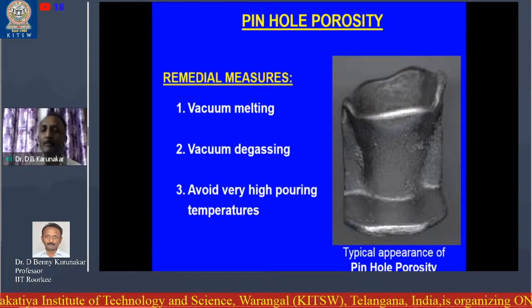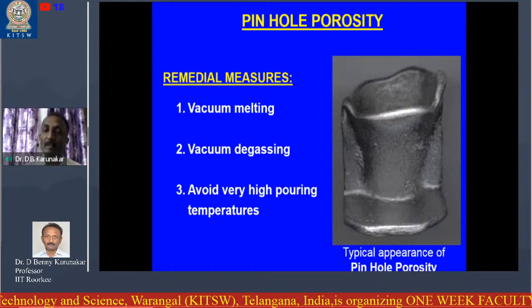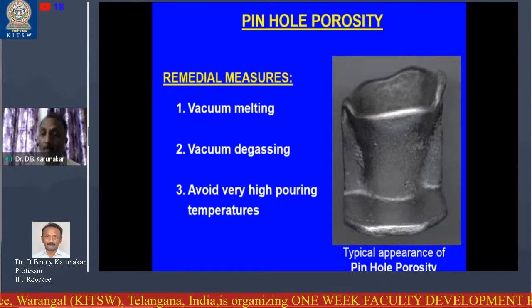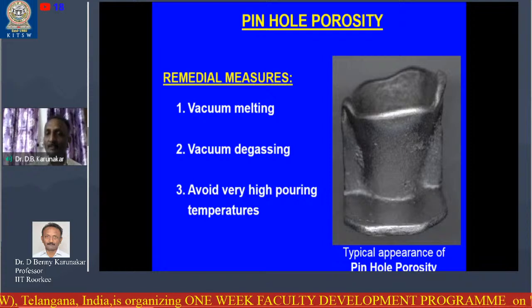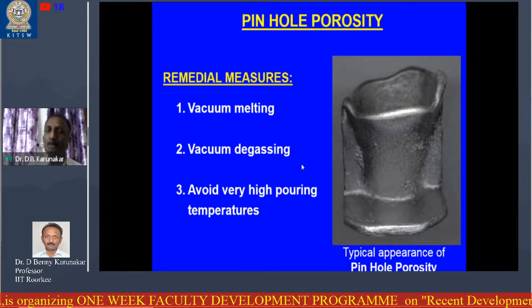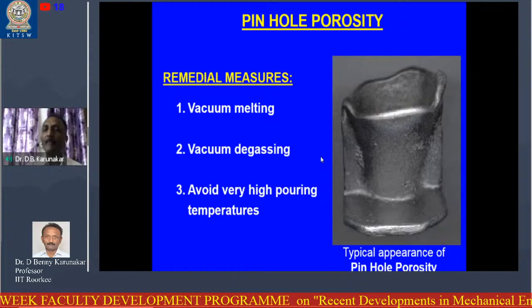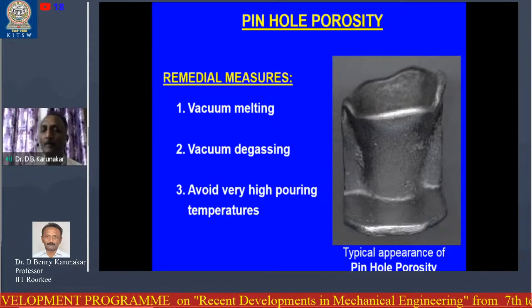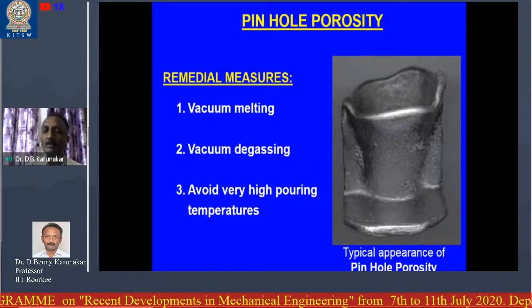What happens if someone heats it up to 850? It overboils. Then it accumulates air bubbles inside, and that could lead to pinhole porosity. So the superheat should be optimum, not too much.